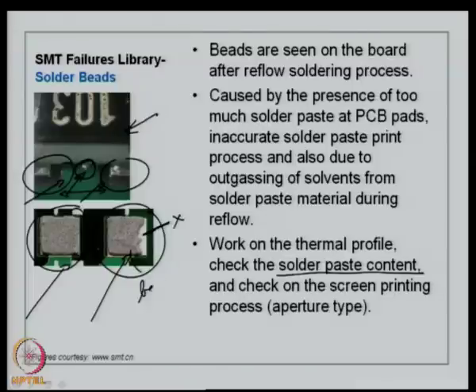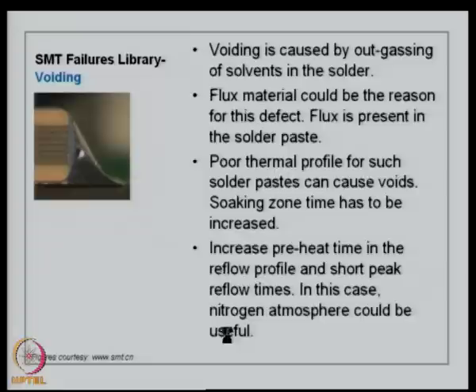You can see bead formation already, because at room temperature or during tacky cure you can see that the solvents have gone and the solder paste has disintegrated. It is a material that has lost its shelf life, or during the synthesis of the solder paste the media has not been properly utilized in holding all the solder paste material, that is the conductive material, together. That is a very key issue in the synthesis of solder paste. So, thermal profiling plus the poor quality of solder paste could lead to solder beads.